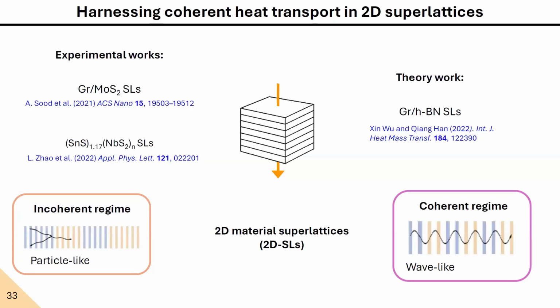The point is that here they do thermal engineering by stacking alternating layers of materials with high contrast in their mechanical properties and phonon properties. They achieve a thermal insulation which is much higher than a single layer of each of these materials of the same thickness. Still, there is no coherent phonon heat evidence in these experiments. But to my feeling, it's just because the material is so thin that you cannot have interference effects. Like the phonon wavelength is probably still larger than their thicker material.